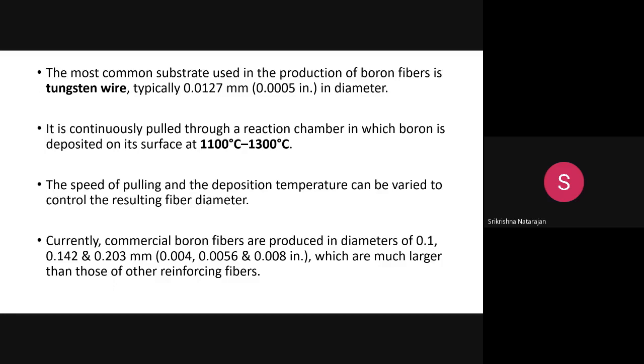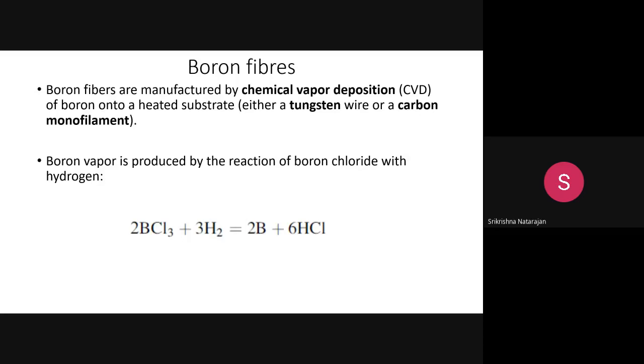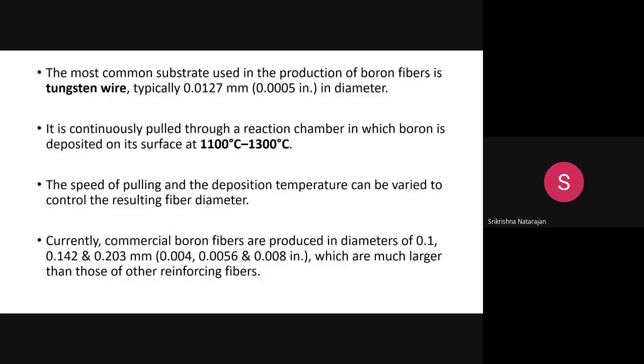This reaction happens at a very high temperature of around 1100 to 1300 degrees centigrade. At this temperature the boron gets formed. The tungsten wire is continuously pulled through the chamber where hydrogen and boron trichloride undergo reaction. You can change process parameters like pulling speed, deposition temperature, and wire diameter to get better boron reinforcement.